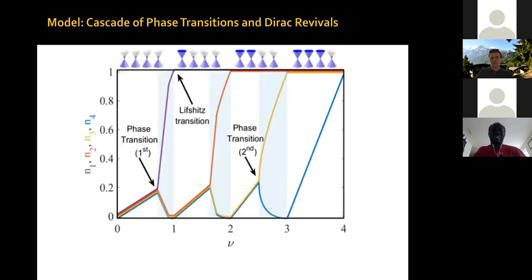this is also telling you something very important, okay? Which is that in this phase diagram that I mentioned earlier, as a function of doping, the ground state of your system is very different before an integer filling and after an integer filling, okay? Because before you have a state, let's say, which has flavor symmetry, whereas afterwards you have a broken flavor symmetry. And that happens before and after each integer, okay?